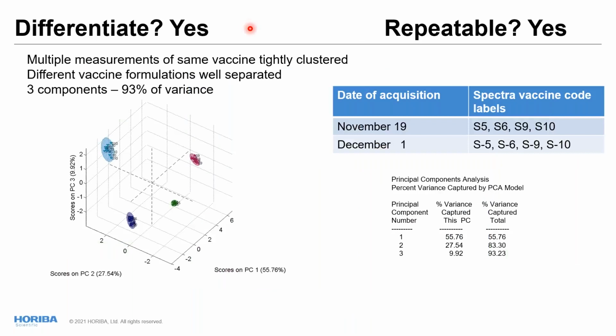So here we took the data. We took 4 measurements of the different components. These are the 2 different days, so the same sample, but with samples taken on different days. And just did a principal component analysis, looking at the scatter by charting the 3 different components. And what we see here is that the samples tightly cluster. So the 10s, the 9s, the 5s, and the 6s are very tightly clustered and very well separated. So these 3 components summarize about 93% of the variance in the sample. And this is a really nice differentiation between these very similar formulations.